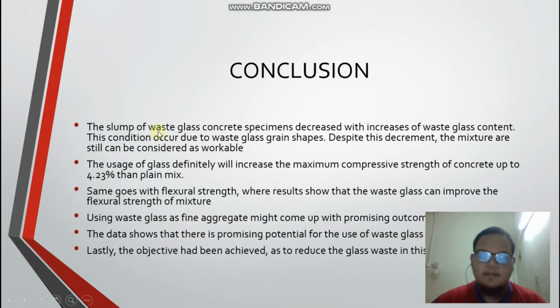So, as a conclusion, the slump of waste glass concrete specimens decreased with increasing waste glass content. This occurred due to the waste glass grain shapes. Despite this decrease, the mixture is still considered workable. The usage of glass definitely increases the maximum compressive strength from the plain mix by about 4.23%. The same goes for flexural strength, where results show that waste glass can improve the flexural strength of the mixture. Using waste glass as fine aggregate might come up with a promising outcome. Lastly, the objective had been achieved, which is to reduce glass waste in this world.